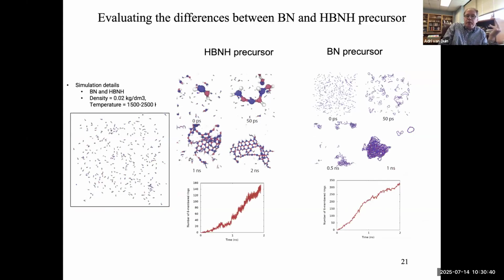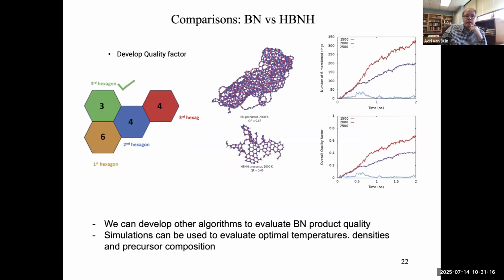And then we can look at what sort of precursors to use. For example, a big question in the experimental literature is, are we going to use an HBNH precursor or a BN precursor? It turns out that an HBNH precursor grows much slower, but you get much better 2D type materials, while the BN precursor grows much faster, but you get a much higher curvature. We grow boron nitride, and it indeed looks like a high curvature graphite. So it depends really what you want. And these simulations are very fast. This is really just a couple of hours of MD simulations, and you can very quickly look at how temperature and how precursor affects the structure.